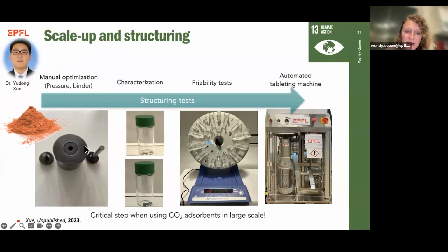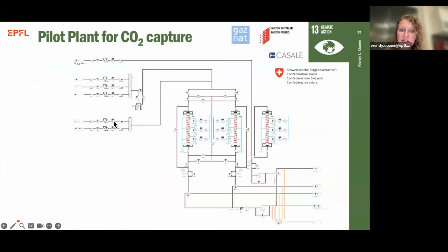So basically what we have to do then is take these fine powders and structure them into tablets. To do that, we're basically using a die like this and a hand press. And then we make these tablets. We're developing different protocols, and then we test how mechanically stable the pellets are. And once we have a pellet that has similar performance to that of the parent powder and also is very robust, then we can transfer this into this automated tableting machine, which can actually make around 2,000 tablets per hour.